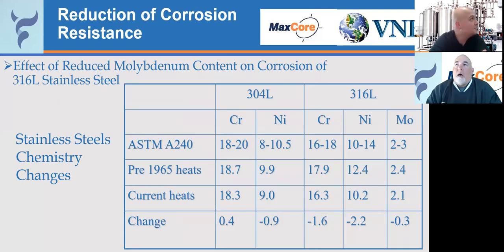So when we're talking about materials, one of the things you have to look at is the steel chemistry changes that have taken place over the last few years. 304 stainless steel and 316L stainless steel, if you look at the pre-1965 heats, you can actually see the chemical composition of these particular materials. The ASTM standard shows that in 316L stainless steel, you have to have 16 to 18% chromium, 10 to 14% nickel, and 2 to 3% molybdenum content. If you look at pre-1965 heats, you can see that we were running around 17.9 chromium, 12.4 nickel, and 2.4 molybdenum.